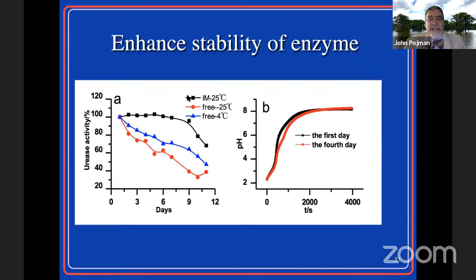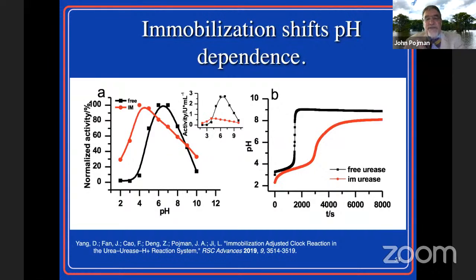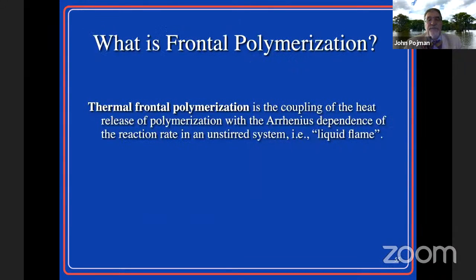So this is the immobilized enzyme versus the free enzyme. You can see it did increase the stability, but we've still lost almost 50% of our activity, and we have only about 25 to 30% of our activity after 2 weeks. So it's an improvement, but it's still not good enough. It did shift the pH dependence of the activity, which is interesting, but not what we wanted to accomplish. We really want to control this polymerization. So that's where we stand. This is a great system to study, and we're making lots of progress with it.